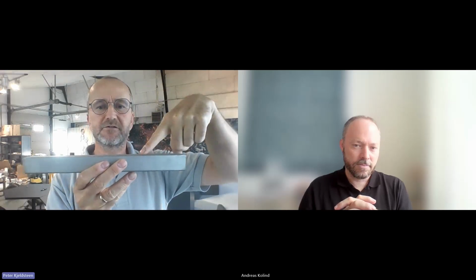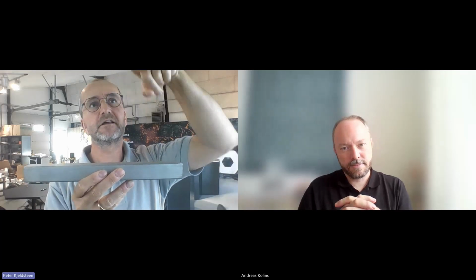We also make trials with this to heat up gas. And maybe that is the biggest differentiator of this technology compared to other electrical heating systems. When you have a standard heating element, it could be a rod. Then you want to heat a gas, and the gas comes in, it hits the surface, it's heated up, and it bounces off. But this gas molecule is not heated again until it hits the wall or hits the heating element again. It means that the activity of the surface versus the amount of gas you have to heat is extremely low. But in our case, we have a surface area inside because we blow the gas through the channels,